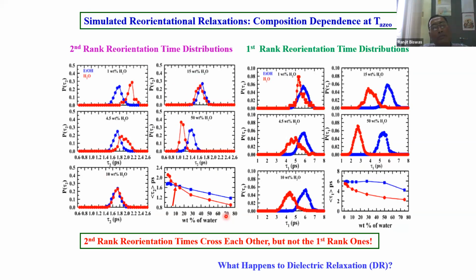Then we thought that we should look at the second rank reorientation time, because that second rank reorientation time you can probe by 2D IR measurements, and people have done that. And what we saw when we did that is that the distribution of rotation time of water is actually overlapping perfectly, but at a mole fraction different from the mole fraction at which the center of mass diffusion coefficient distributions merged, which is 10 weight percent.